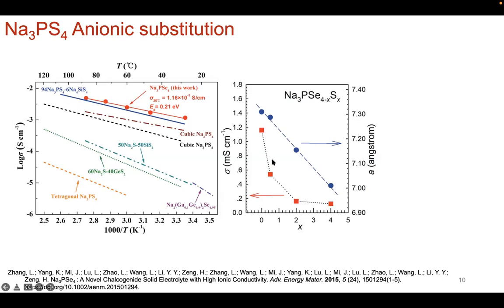What you also see is if you leave the cation alone and you only mix in anion, ionic conductivity also increases as a function of how much selenium you put in. So in terms of increasing this selenide content, that does increase the disorder, and you see the increase in ion conductivity. But typically, what one has to consider is what we'll talk about next, which is the electrolyte interface.